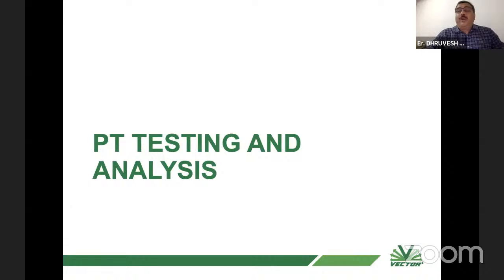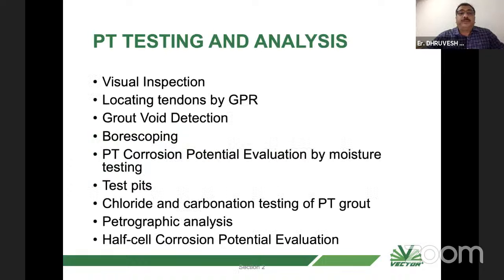So if we have grouted tendons and issues with voids, segregation, or moisture or water remaining there because of bleeding, how to test? You can have various methods, which I will take one by one, which include visual inspection by opening, locating tendons by GPR, grout void detection, boroscoping, PT corrosion potential evaluation by moisture testing, test pits, chloride and carbonation test, petrographic and half cell potential evaluation.